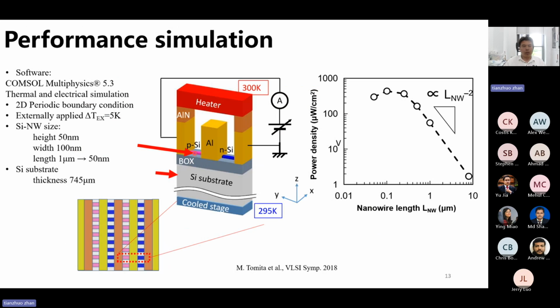And we did some performance simulation. With this structure, we changed the length of the silicon nanowires from 1 micrometer to 50 nanometers, and we found that the power density has been improved by 100 times by shortening the length of the silicon nanowires.